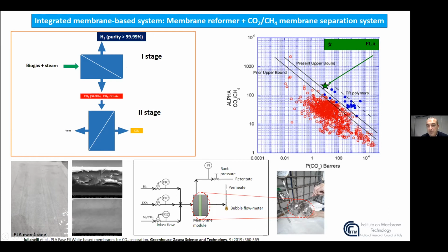In this graph, it's possible to observe our results at room temperature, in which the selectivity CO2 versus methane is higher than 200 with respect to a permeability of CO2 through the polymeric PLA membrane higher than 10 barrer. And this is just a proof of how the two-stage process based on membranes is possible and available to produce high-grade hydrogen and capturing CO2 in order to meet the requirements of blue hydrogen generation.